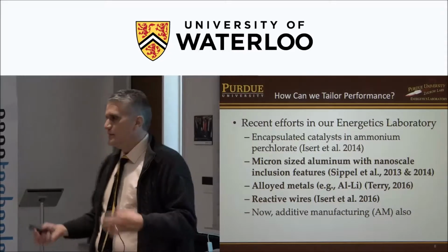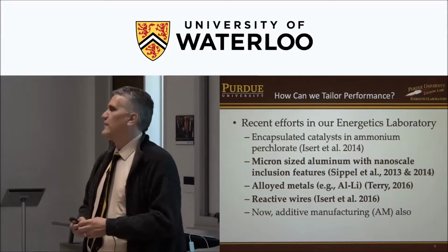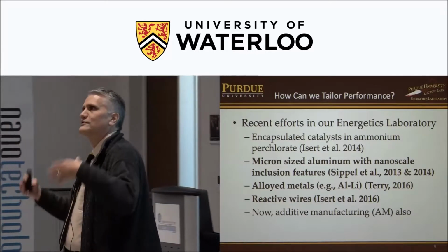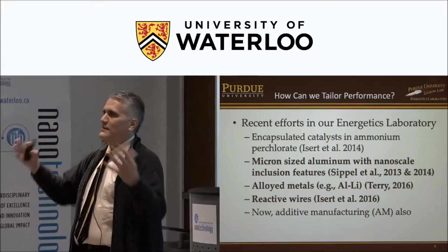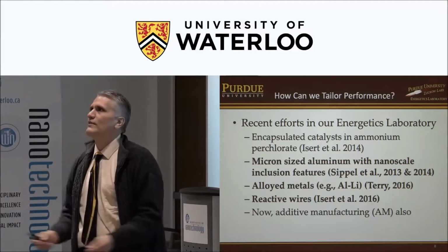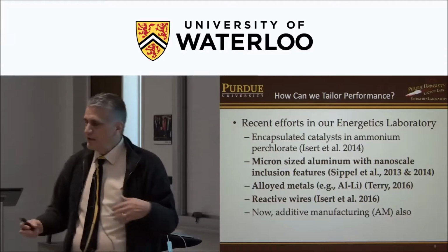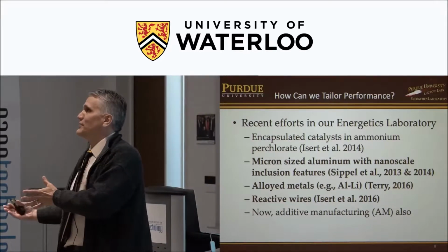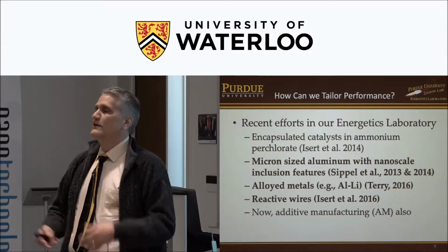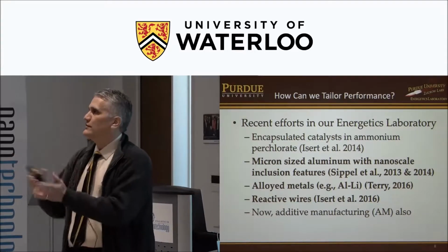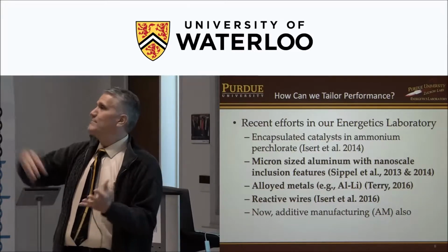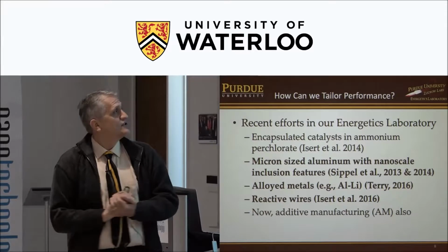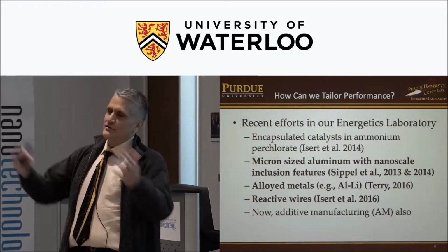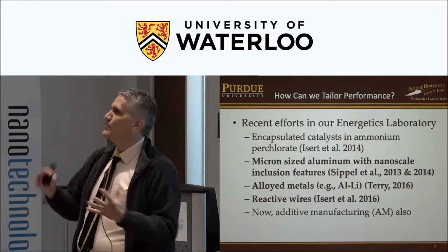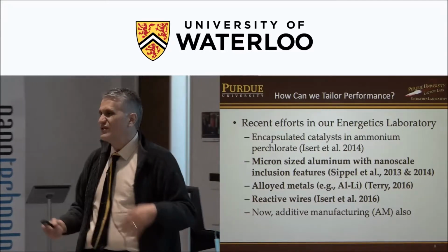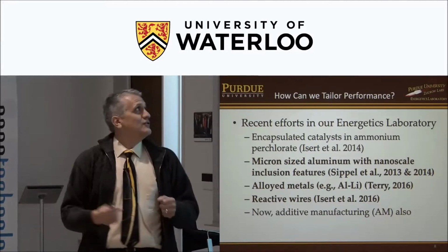One other effect is, if you think about this composite material, it has to have good mechanical properties, because if it starts to form cracks inside your rocket motor, the flames will go down to the cracks, and that'll open new cracks, and then you have an explosion rather than propulsion. And with catalysts, you want high surface area. They work better if you have more surface area. So you like the nano size, but if you want to put that into your propellant, you have to sometimes add more binder if it's a really high surface area catalyst. And you don't want to do that because you're starved for oxygen already. You're trying to bring in as much ammonium perchlorate as possible. So to bring in a really high surface area catalyst, you have to sacrifice performance.